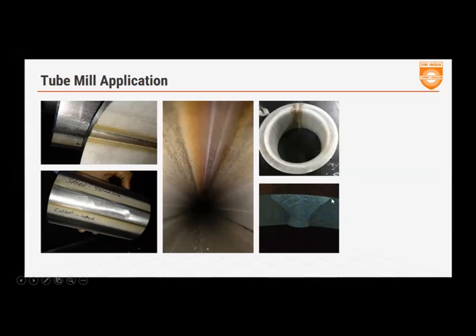On the tube mills, there's a word of caution. They have something called near weld thickness, which needs to be equivalent to or above a particular level. But in tube mills, the tolerance allowed is about 12% on the thickness. So they typically use a lower thickness material. So filler wire is suggested or recommended when you have higher thicknesses to take care of your near weld thickness. Otherwise, from the joint strength, there is no problem.